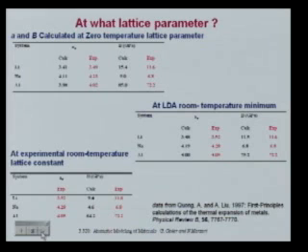So here, the bulk modulus is calculated at the zero temperature lattice parameter. That's what you would typically do. Say for lithium, the lattice parameter that you calculate, this is in LDA, is 3.41. And you get a bulk modulus that's 15.4 gigapascal, and experimentally it's 11.6. Just like you expect, it's too stiff, very typical in LDA. Same deal for the other metals, although for aluminum it's not as bad.